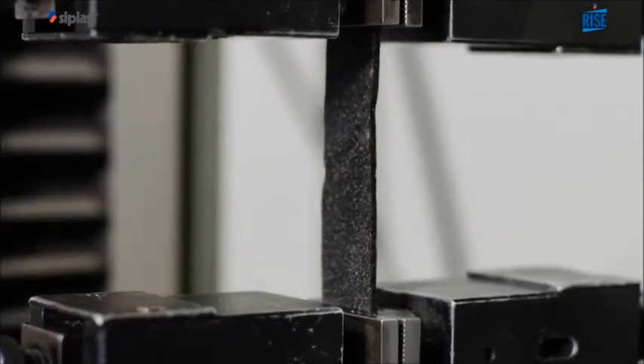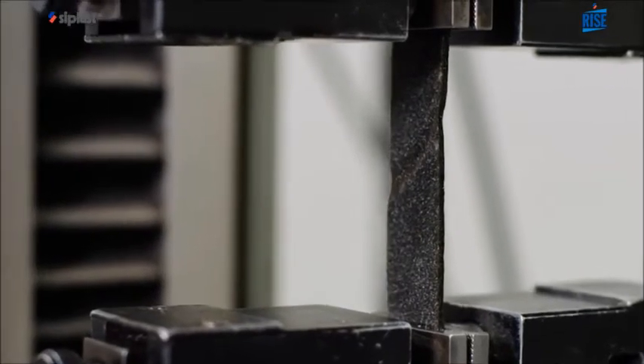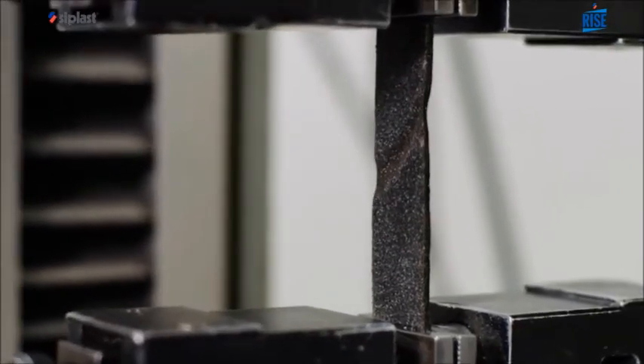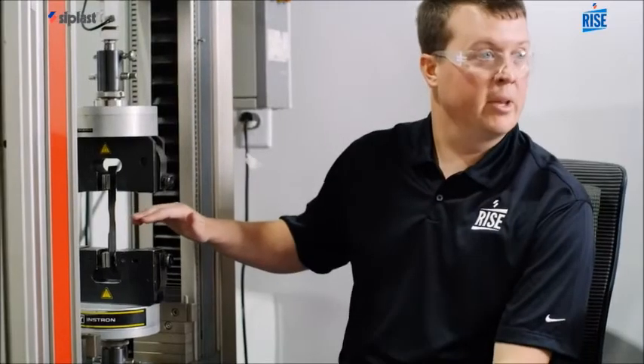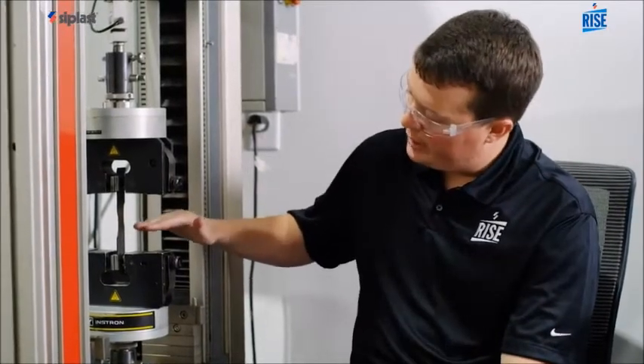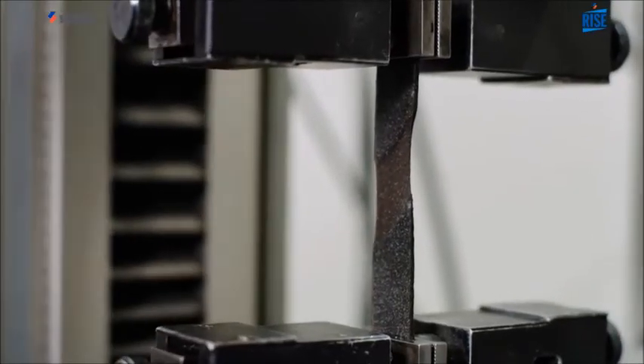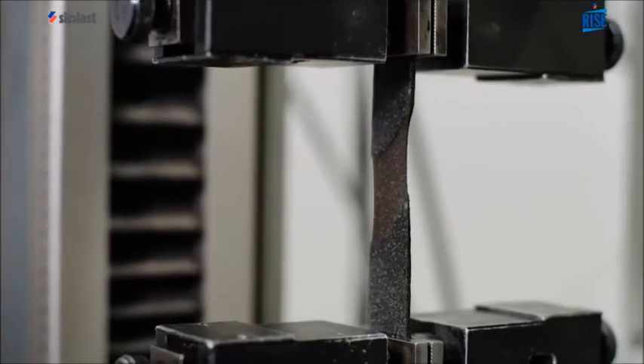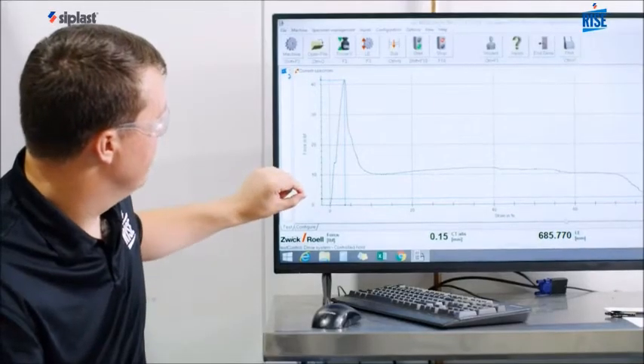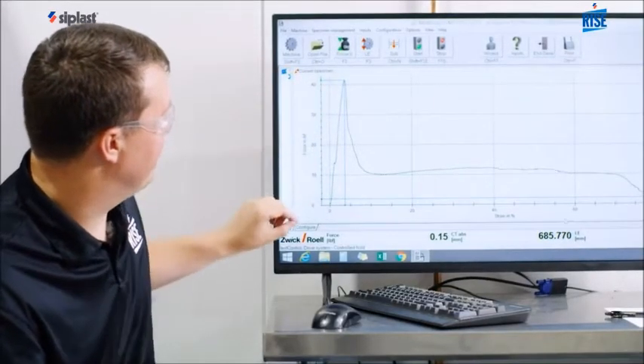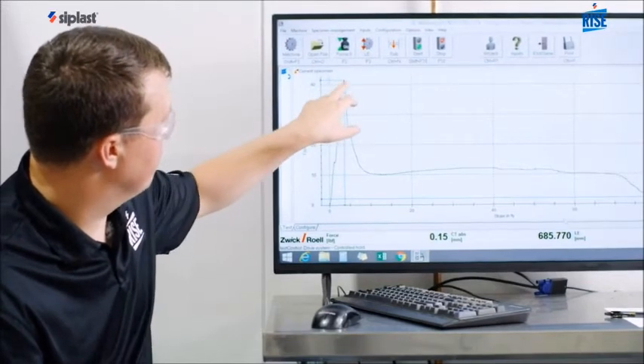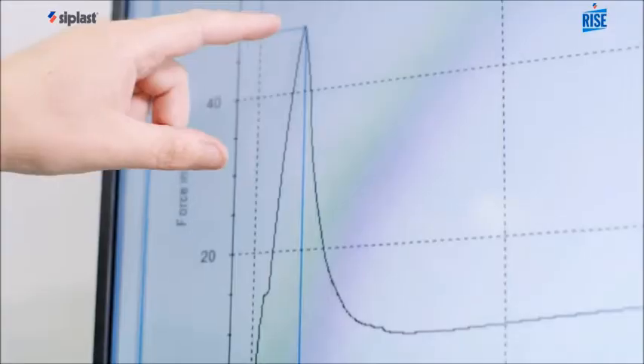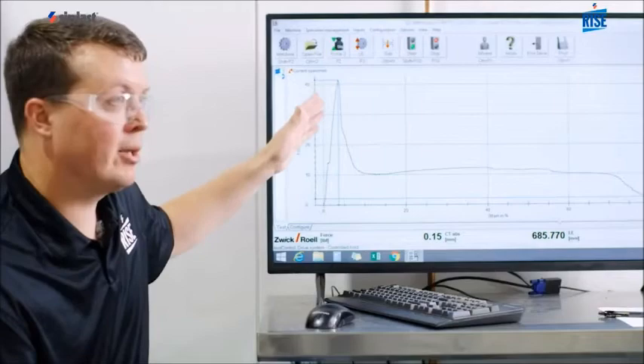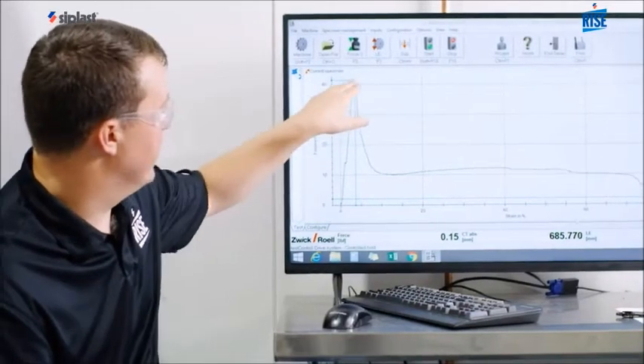The reinforcement's been broken, so this is all elongation of the blend that you're seeing. You can see that nice amber color of the blend, and that's showing the elongation of the blend itself and not the fiberglass anymore. Here on the y-axis is where the force is measured that was applied to that sample. This is the break point, where the peak load, the tensile strength, is reached right here.